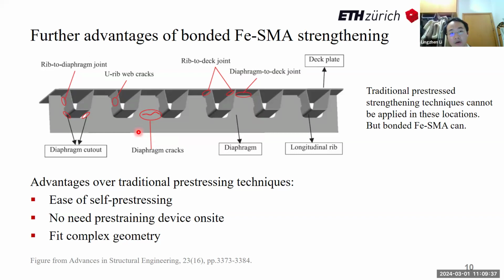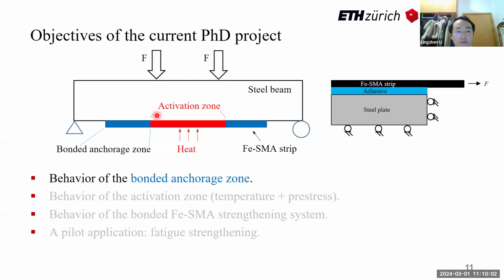My colleagues and I already tried it at the lab level. We bond short shape memory alloy patches, for example 100 millimeters long or 200 millimeters long, and heat the center part. For example, bond a patch here and heat it. Prestress is generated, and the generated prestress helps us to close the crack, and the strengthening is done.